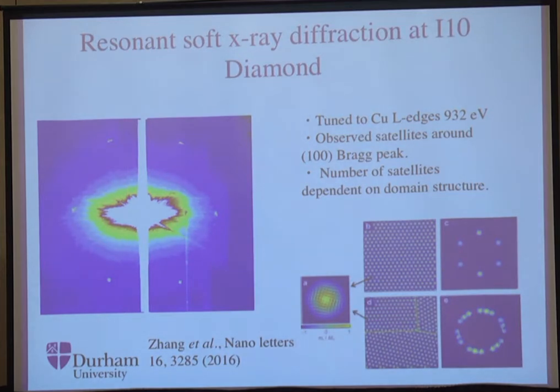And here are some simulations. If the Skyrmion lattice is uniform throughout, it's effectively a single crystal or single plane. With the triangular lattice, you would, of course, get just this hexagonal pattern of satellites. Whereas if you have multi-domains, here we've got 3, this is a simulation, then you would get 3 spots around each. Presumably, LANL just happened to have 2 in theirs.